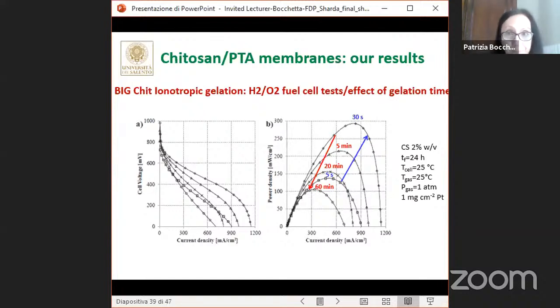I would like to show you the results obtained at our hydrogen-oxygen single fuel cell. You can see here the polarization curve and power output relating to different times of gelation. And you can see that the best performance is delivered from 30 seconds of gelation time for 2% weight volume of chitosan concentration. So these are the conditions identified as the best condition of synthesis.